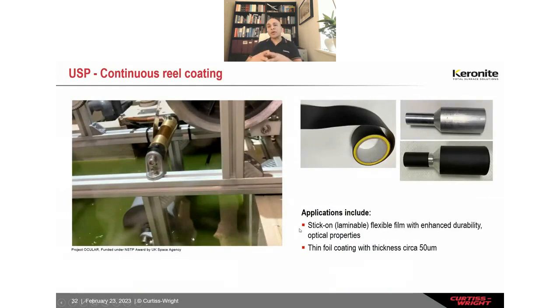The next one we thought about, okay, why not use this technology also on foils? Of course, anodizing has been done for many, many years. The kitchen foils are probably anodized, very thin coating, a few nanometers, but now we're talking about a thick engineering coating. So what we did here is we coated this 50 to 70 microns thick foil, rolled into about tens of meters, and we coated this in a continuous mode.